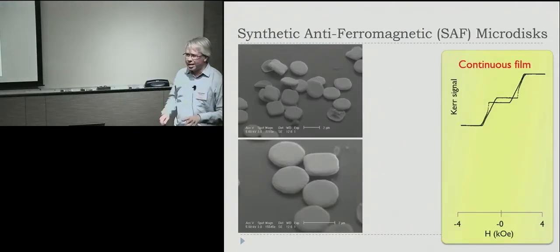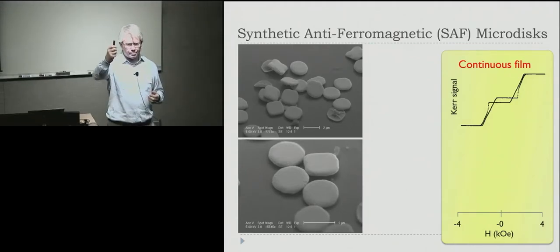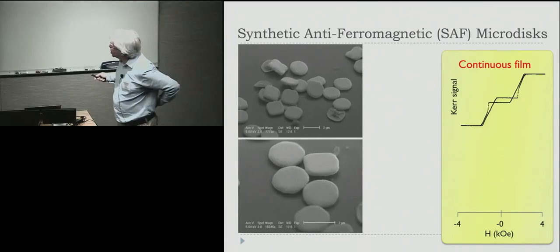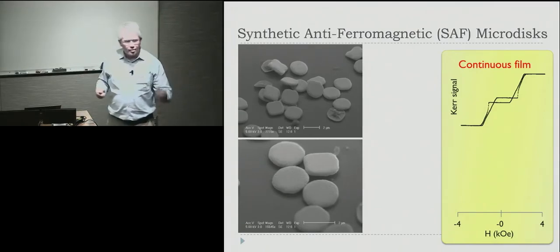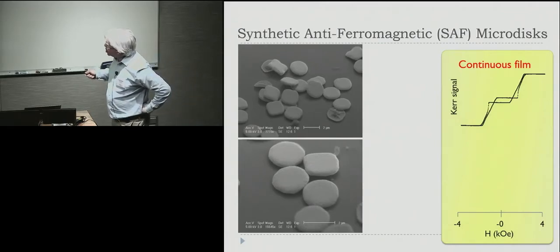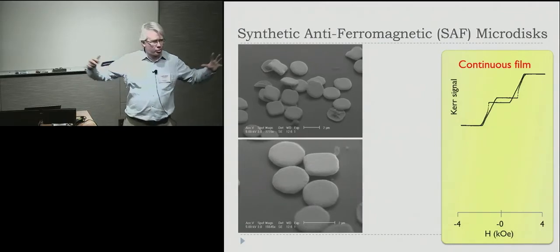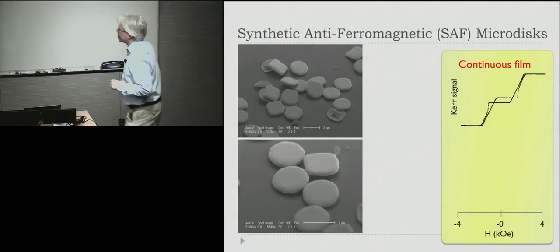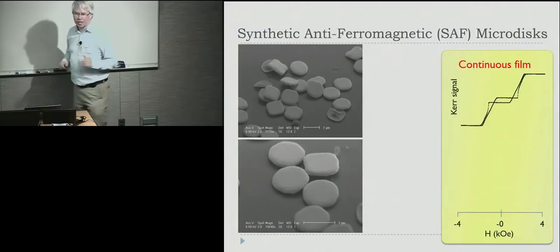In this case, we've made a synthetic magnetic liquid, and then we've dropped it back onto a wafer and let it dry and looked at it under a microscope. And these little ravioli that you see, these are the little packets of multilayers. And you can see they're just lying randomly next to each other. They're not all agglomerated into big chains or lumps. So we can see that the compensation strategy is working.